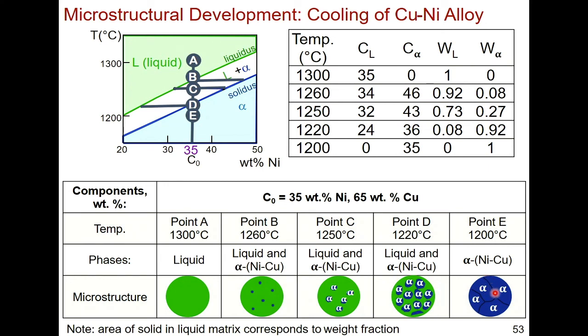And this black line right here, and right here, and right here, and right here, that's to indicate the grain boundaries, right? When we talked about polycrystallinity in imperfections, we talked about how grains can orient themselves in whichever way, unless you're trying to grow a single crystal, like in the Bridgman method or the Czochralski method. If you have a polycrystalline material, you have grains oriented in whichever direction. So that's what it's representative of, is that these alpha grains are polycrystalline, and that's what you have if you're just dropping down the temperature and it's isotropically cooling. Okay, we're going to pick up on eutectic phase diagrams next time.